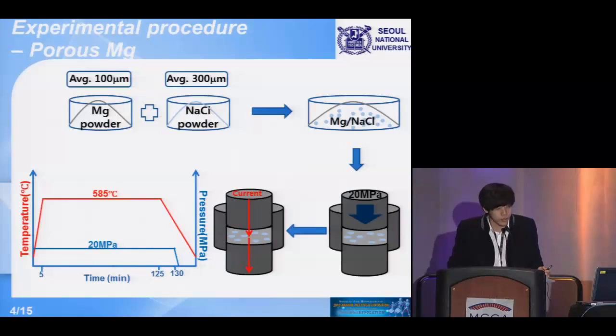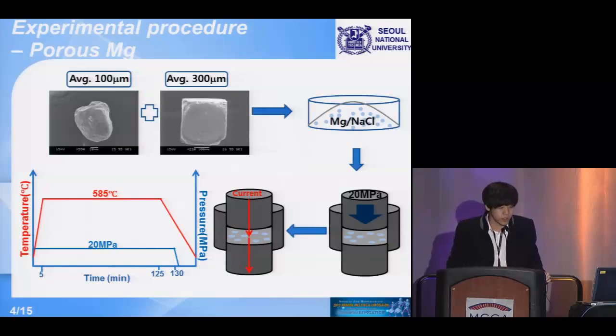We mix magnesium powder and sodium chloride powder. We use the space holder method with the sodium chloride as a spacer. These are the SEM images of them, and after mixing them uniformly, we put them inside the copper mold and press it with 20 megapascal pressure, and then we gave the pulsed DC current. This is the brief condition of our experiment. We increased the temperature up to 585 degrees and maintained it for 2 hours.